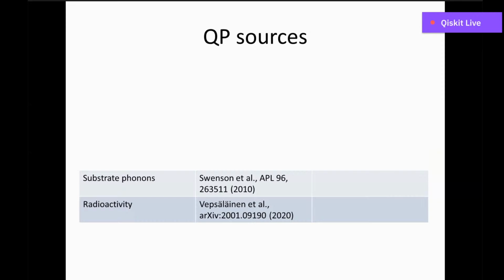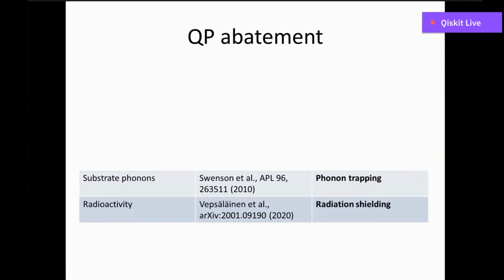The two quasiparticle sources that we want to deal with then are phonons in the substrate, which can or cannot be generated by radioactivity, as was first pointed out by Swenson and co-workers, and radioactivity itself. To get rid of them and to better our superconducting circuits, respectively, we can implement phonon trapping and radiation shielding. And this will be the subject of the rest of my talk.